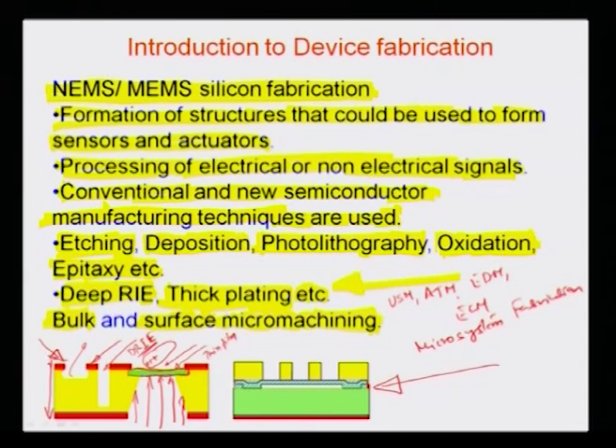To exemplify some, let us look at this illustration here. So, here for example, this is a polysilicon layer which has been put in a manner so that you had a sacrificial layer in this particular region given by the dots. It could be a resist layer, and then you have deposited the polysilicon layer on the top of this resist layer, and then later on you can remove the resist layer away because polysilicon is a high strength material, so that you can have a channel on the surface on one side and buried within this polysilicon layer on another side. So, you can remove away this resist later on, it just goes off, thus resulting in this channel into the plane of the paper or plane of this transparency slide.